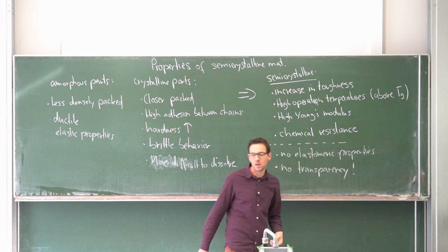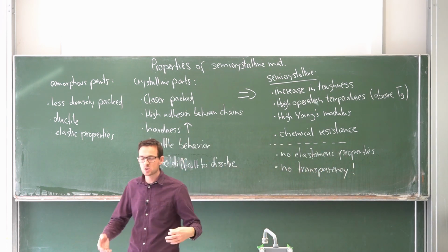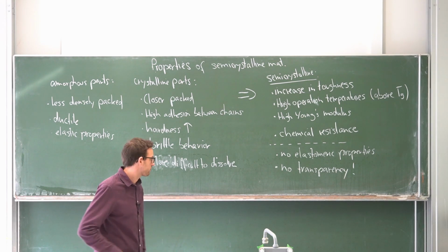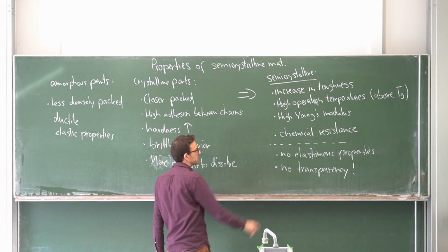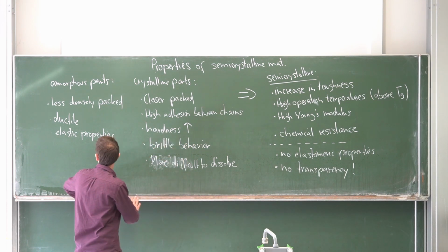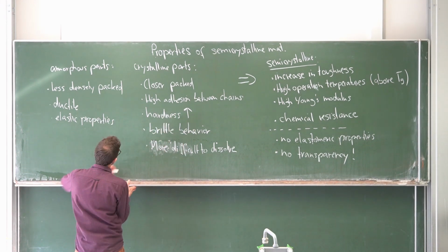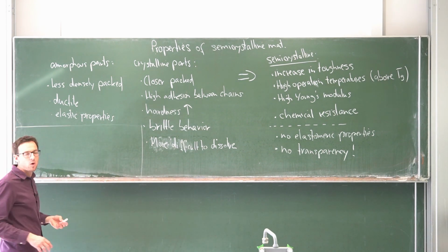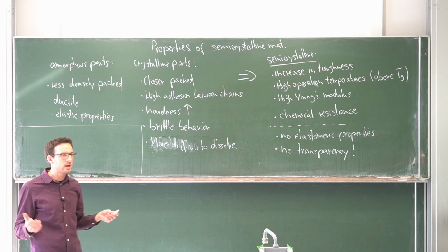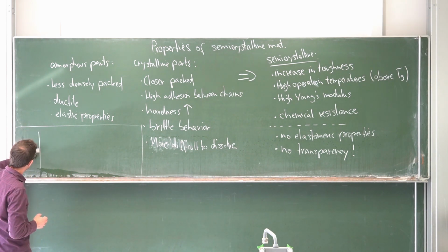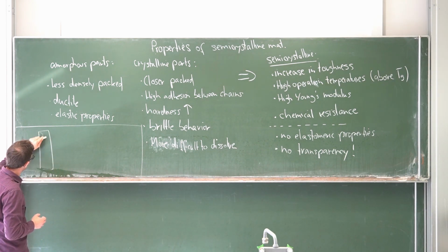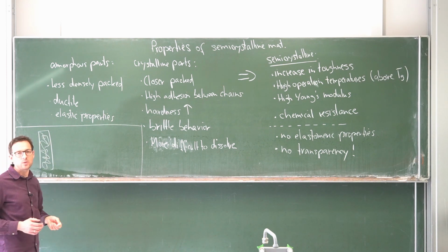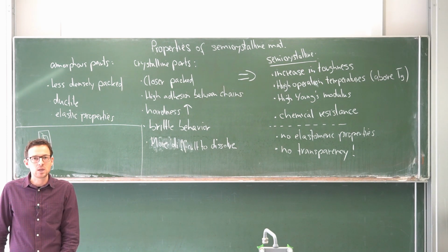So this is really a key disadvantage, or also a way to spot semi-crystalline polymers is to look at the optical properties. And semi-crystalline polymers cannot be transparent. Why is that? Maybe we can just put this here. An amorphous polymer consists of a single phase. So if you look into your material, it just has polymer chains, and the refractive index is equal everywhere.